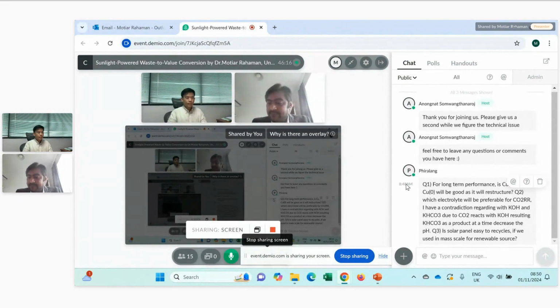Which electrolyte will be preferable for CO2RR? It depends. So bicarbonate is quite good. It has quite good solubility of carbon dioxide. For neutral condition we mainly use potassium bicarbonate saturated with carbon dioxide. You get around pH 7, and that's a quite strong buffer. It doesn't change.